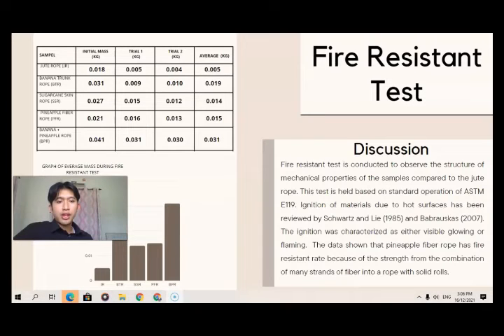My name is Muhammad Wafir Hekal bin Muhammad Azhar, and I will be continuing the presentation by talking about the fire resistant test. Fire resistant test is conducted to observe the structure of mechanical properties of the sample compared to the jute rope. This test is held based on standard operation of ASTM E119. The ignition of material due to hot surfaces has been reviewed by Schwartz and Lie and Babrauskas. Ignition was characterized as either visible glowing or flaming. The data shows that pineapple fiber rope has a good fire resistant rate because of the strength from the combination of many strands of fiber into a rope with solid rolls. As you can see here, there is the data that we have acquired.